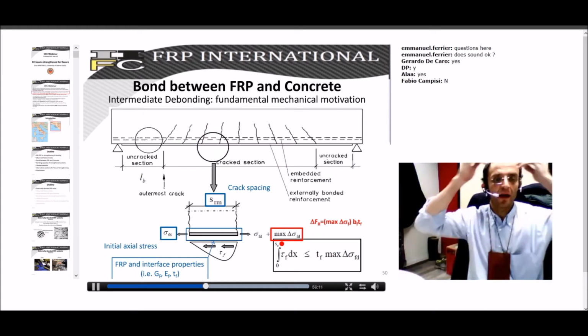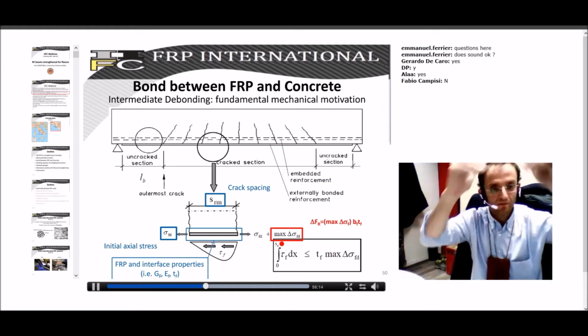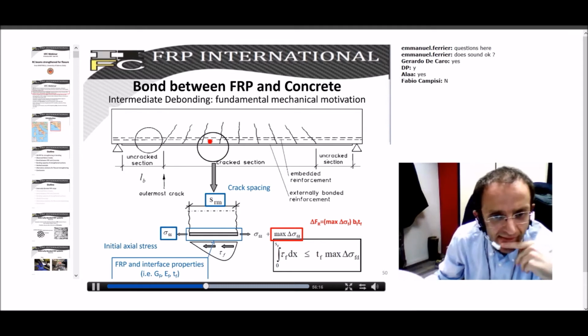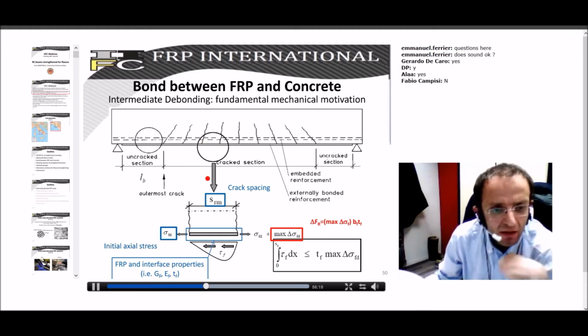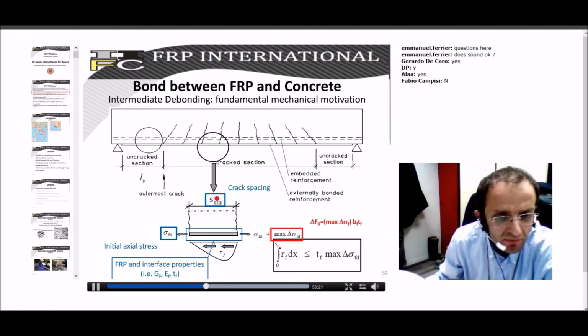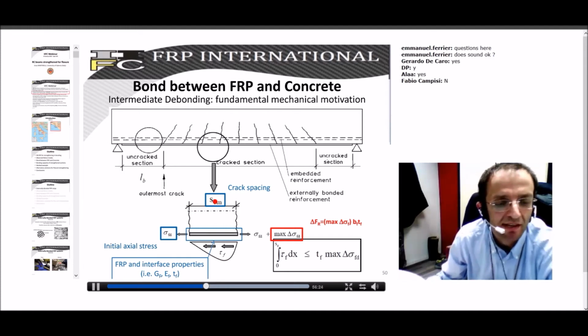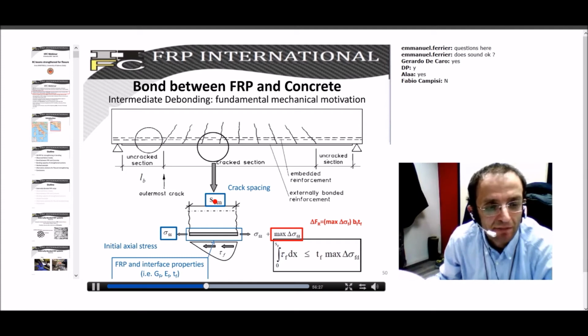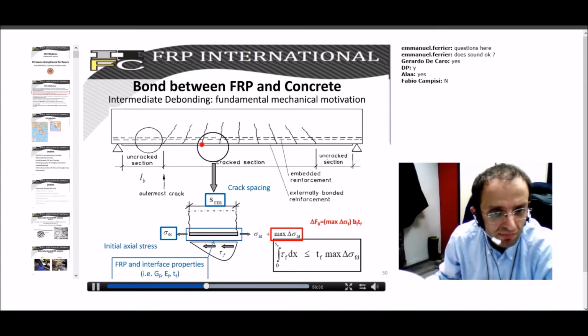Let's try to understand how this phenomenon works. So we have these cracks whose distance is SRM. This is the symbol usually adopted for describing the crack distance. We have an FRP strip which is subjected here to a certain sigma F, an initial value of sigma. And in the other section, we have a sigma which is probably bigger because the moment increases in this way, up to the midspan.